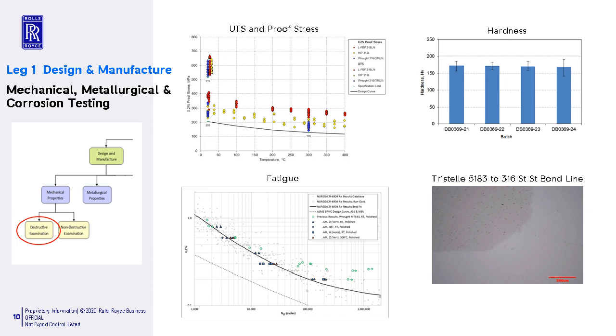Metallurgical tests included chemical analysis, grain size, cleanness, macro, microstructural analysis, also looking at the 316 to Tristelle bond line in detail, and also corrosion testing, so stress corrosion cracking, pitting, crevice, and intergranular cracking. All these assessments really looking at the material behaviour and looking to understand if it has similar characteristics to its wrought equivalent.